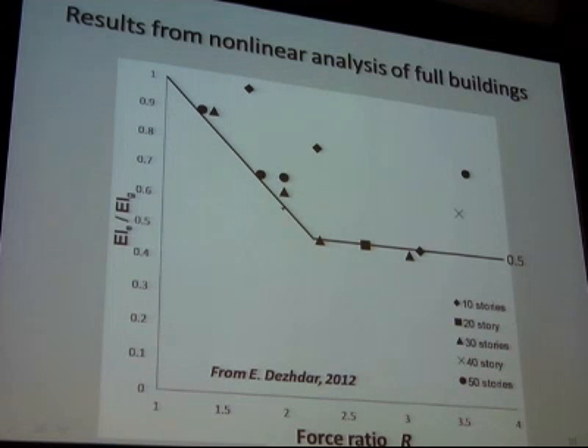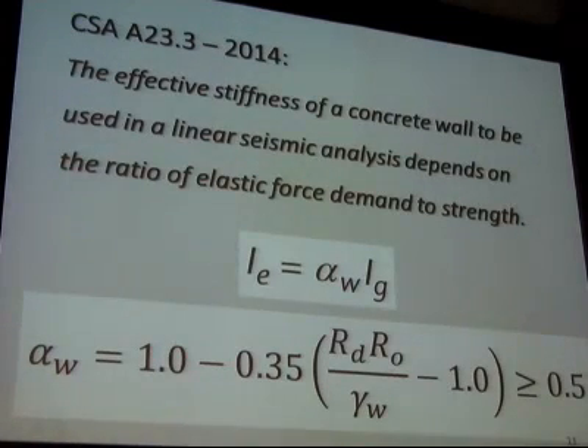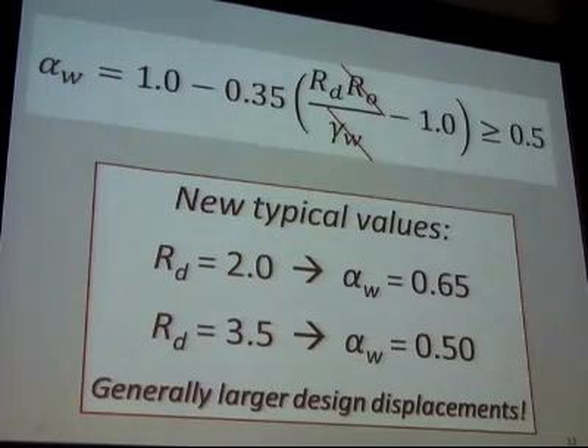Anyway, so again, just to summarize, what you want to do is relate the effective flexural rigidity to the strength rather than to the axial load. And in fact, here's the expression at the bottom that's been proposed for the code and is in the code. And just to simplify it, one of the simplifications the committee came up with is saying we can assume that the RO is equal to the overstrength. And so you end up with a very simple expression where the effective stiffness is a function of the RD value you use to design the wall.